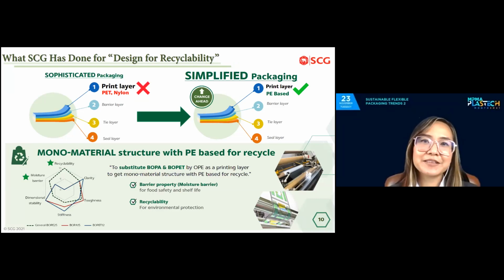In commercial scale, oriented polyethylene printing layer can give a lot of benefits. For example, barrier property like a moisture barrier to extend shelf life of the product. And the other important thing is the recyclability for environmental protection. However, oriented polyethylene printing layer cannot fulfill all requirements of the conventional printing layer, especially the film clarity and stiffness. But this gap can be improved by other technology solutions, for example, processing technology like biaxial orientation or machine orientation, and also the film formulation in parallel.